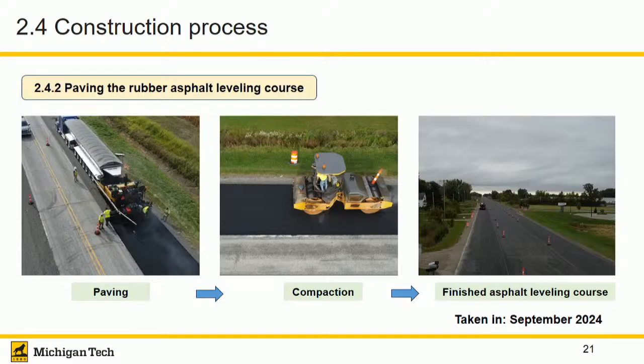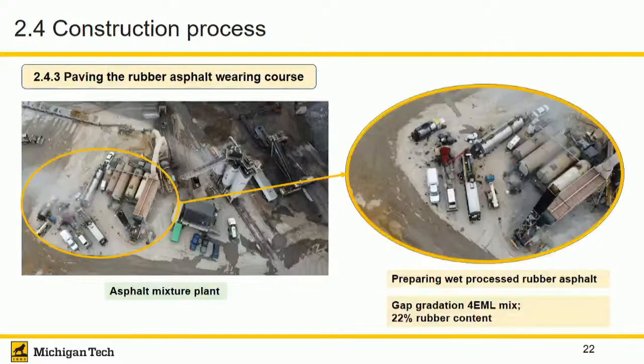Of course, this is the wet process. The previous project I mentioned to you was actually the dry process project. Here's the wet one. So because of 2 layers, they get the first layer on, and of course, after that, we get a wearing course, same process. But the good thing for this project was that the 2 layers use the same asphalt materials. Of course, we also have the other 6 miles of roads. Those are the control materials we are using. Those are using DOT's standard mix design.